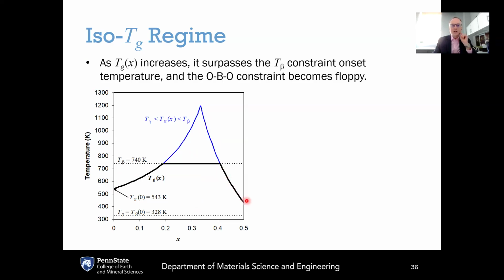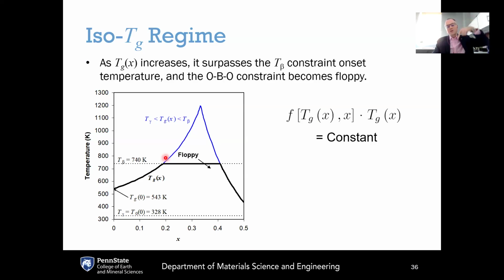There's one complicating factor, though, which is that eventually the glass transition temperature violates one of our assumptions, which was that it falls below T beta. And in fact, if we have T beta placed somewhere here, if the Tg goes above T beta, that means that all of those beta constraints are no longer providing rigidity. If we've heated the system above the temperature where the beta constraints are rigid, then it becomes floppy. And if it becomes floppy, that wants to drive the glass transition temperature back down. But if the glass transition temperature goes below T beta, then those beta constraints become rigid again, and that wants to drive it back up.